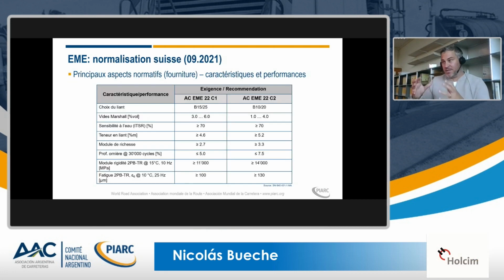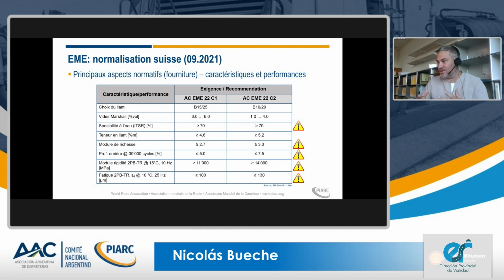Going back a bit to the standard, as I told you, we have two types, the C1 and C2. Basically, for high modulus asphalt, we need a very low penetration binder, 10/20 or 15/25. And what is interesting, first, we have this water sensitivity aspect, the ITSR ratio, which from my perspective is a bit of a joke because we have a limit value of 70%. This we can reach quite easily.